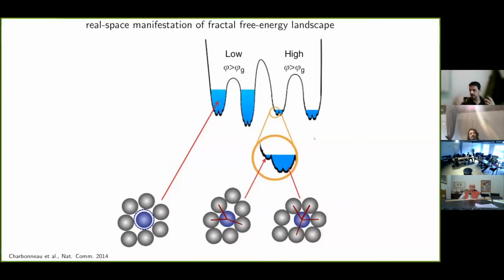If you think about the contacts formed between the particles due to the fractality of the free energy landscape, what will happen is that if you run the system in the Gardner phase, you let it evolve, and then you do a crunch, that means that you compress the system very quickly, and then you look at the identity of the contacts that are formed at the isostatic state, at the jam state that you can no longer compress further. What you would find is that when you're in the Gardner state, in the fractal free energy landscape, the identity of the contacts that you form at the jam state are each time going to be different. Whereas if you have not yet reached that state, then the set of interactions, even though the system is in the glass and doesn't diffuse, will fluctuate around one well-defined inherent structure.